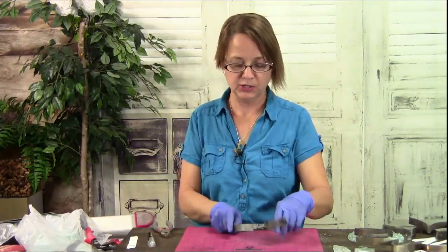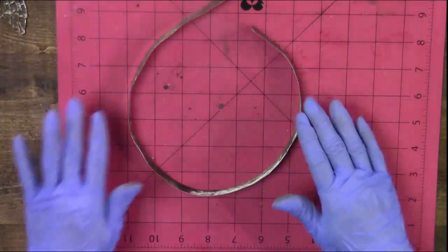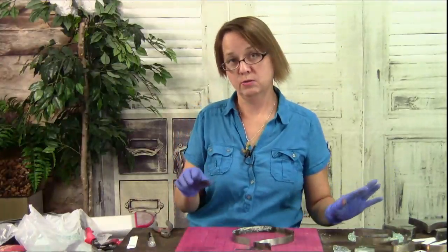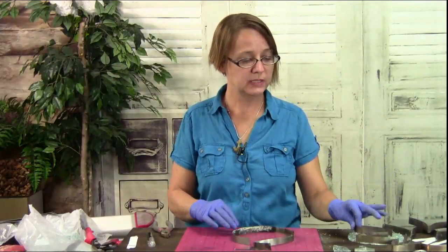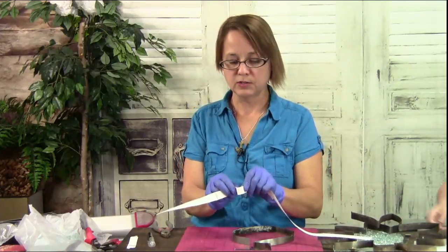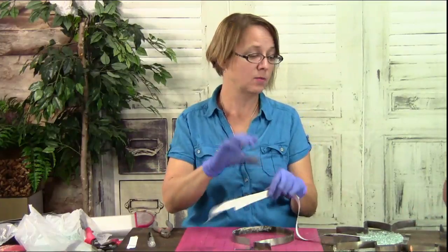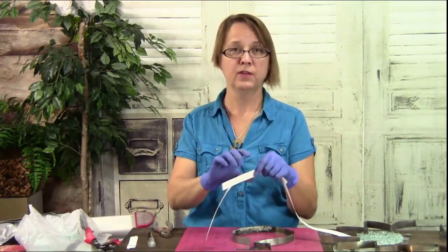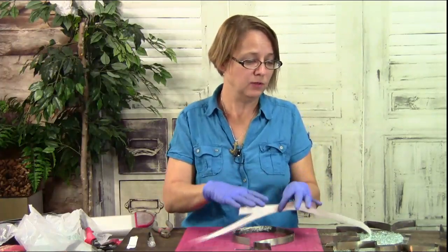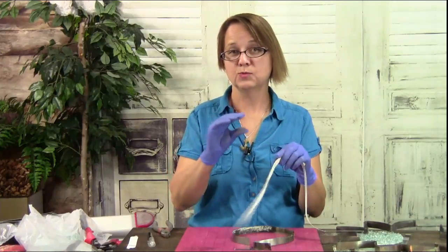Okay. And yes, but if you're going to do the anchor, use the thinner ribbon. This is the 3/4 inch, and it will be a little bit harder to bend. The other thing that you can do with the thicker ribbon, which is in the bigger pieces, which is kind of cool, is if you double up your fiber, if you double up your shelf paper, so you have two layers, you can actually stack your glass really thick, even up to 1.5 inches, because it will lose volume as it tack fuses down. So then you can get a nice, really thick piece.